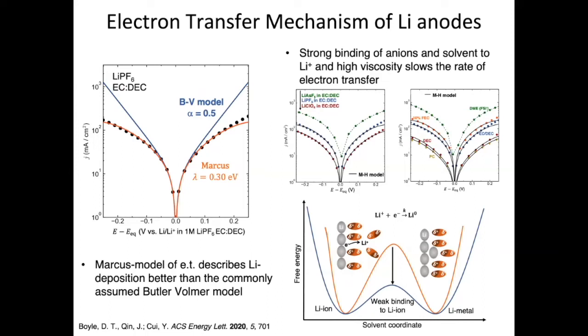And for this arsenic fluoride one, the current density is very high, and your exchange current is much higher than perchlorate and phosphorus hexafluoride. And the reason is this arsenic ion is much bigger. It bonds weaker with lithium. I mean, your solvation energy right there is smaller. And also, screening different solvents and electrolytes, we also established the correlation: solvation energy affecting the charge transfer, as well as viscosity. So we start to be able to establish very nice correlation of electron transfer across this interface, because this scan is so fast, less than a second. This is really in a situation free of SEI. SEI doesn't grow that fast.